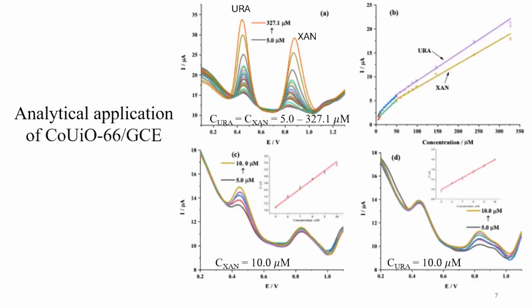We further studied the performance of the electrode for further applications. We found that we can not only simultaneously detect both analytes, but we can also detect a single analyte in the presence of the other one. The presence of either xanthine or uric acid does not interfere with the determination of the other analyte. These electrodes also provided a linear response over a wide concentration range, in either the low or the higher range. When we compare our study with other published studies, we have reasonable results, which means it has potential for further application.